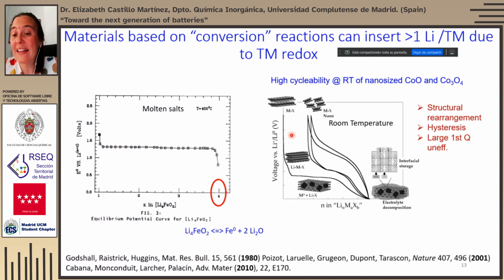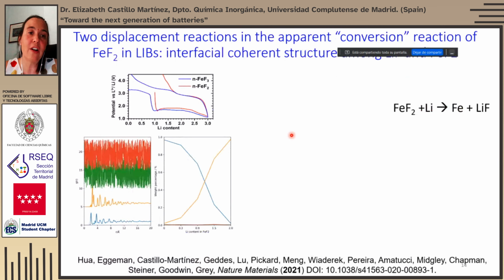Still, the mechanisms of reaction are still being explored. And indeed, for example, for the iron difluoride, rutile iron difluoride, it's been recently discovered that actually the reaction taking place is not just a pure conversion reaction where all the iron fluorine bonds are broken and new lithium fluoride bonds form, but by a study from PDF.